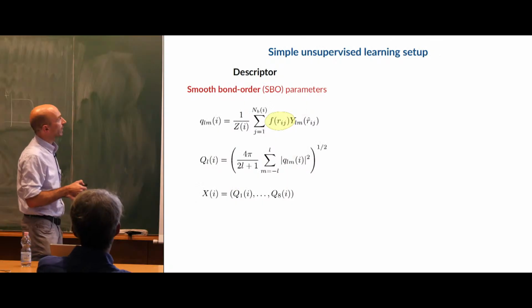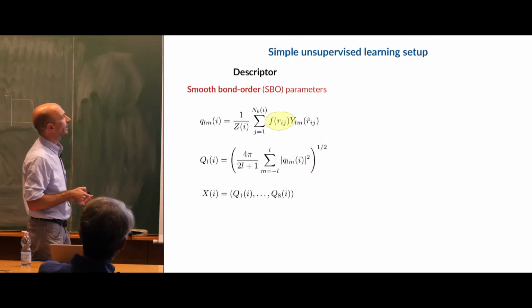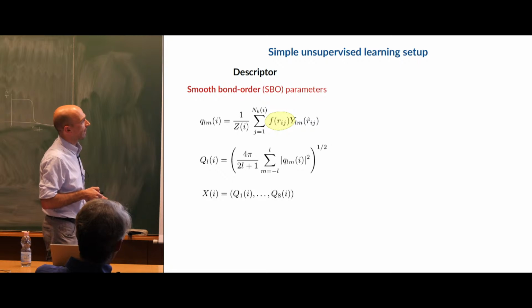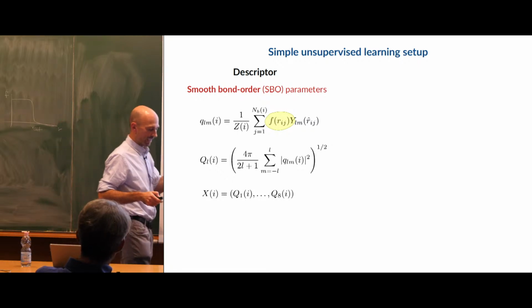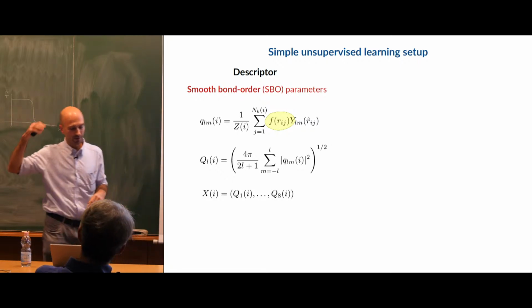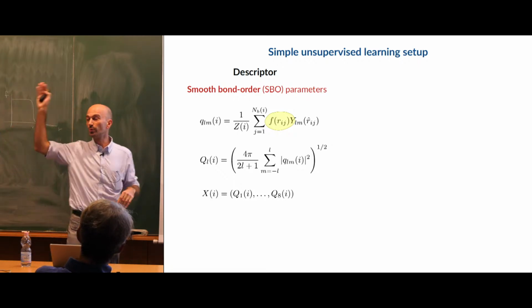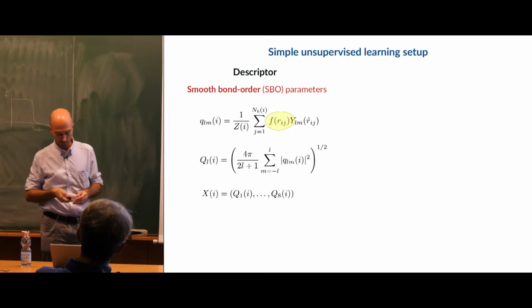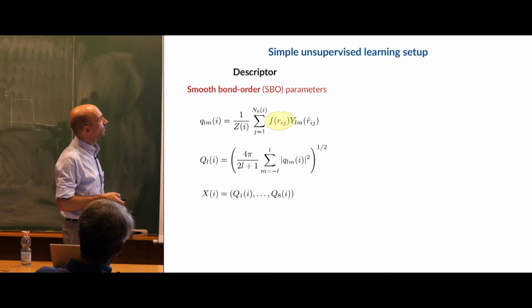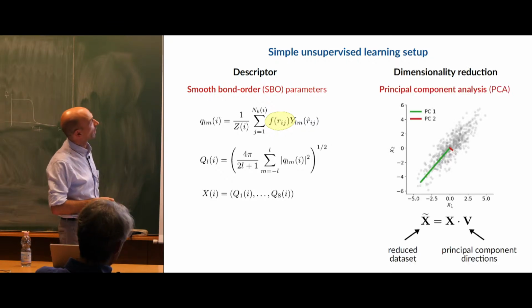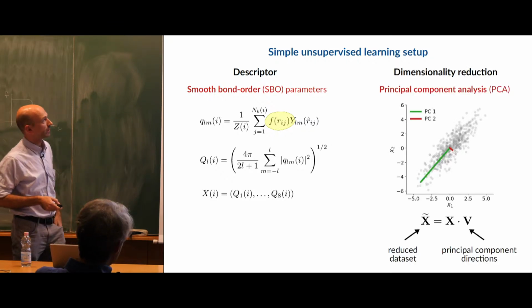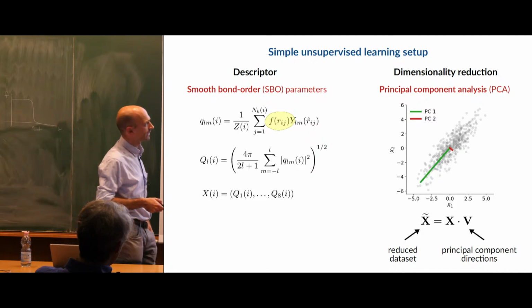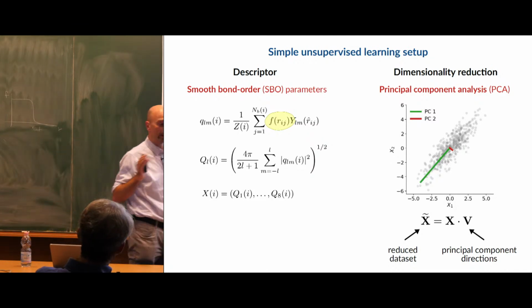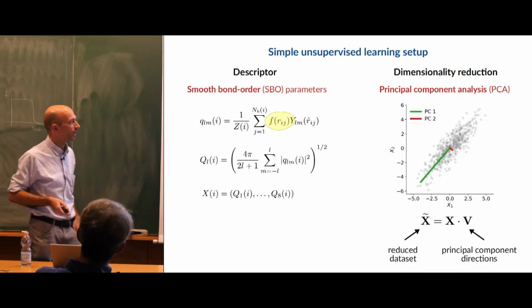And then, of course, we construct a rotational invariance, and we get a descriptor of 8 numbers, the first 8 invariants, and we check that even if you go to, I don't know, 16, the results do not really change. And then we use the simplest possible dimensionality reduction technique, which we heard about this morning, principal component analysis. This is simple, a linear transformation, so we understand what's going on.